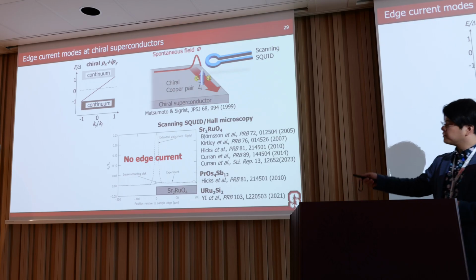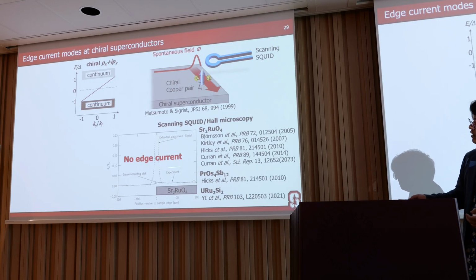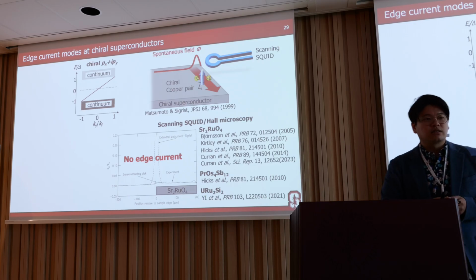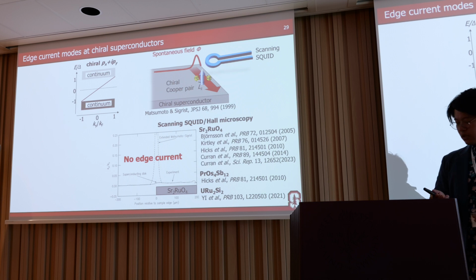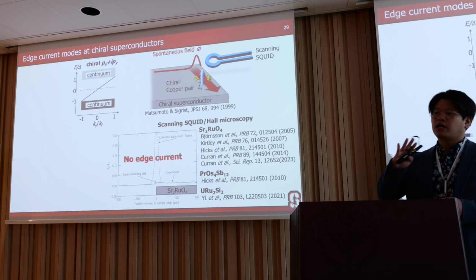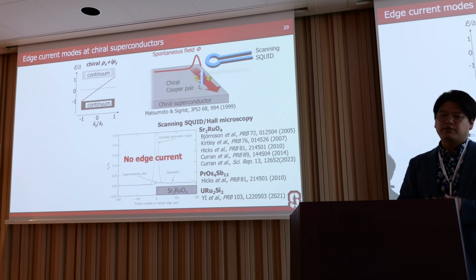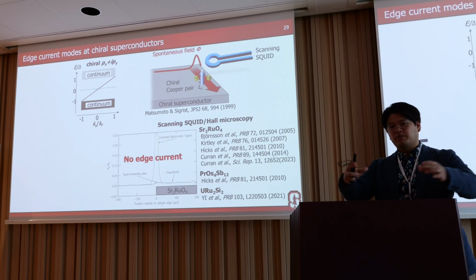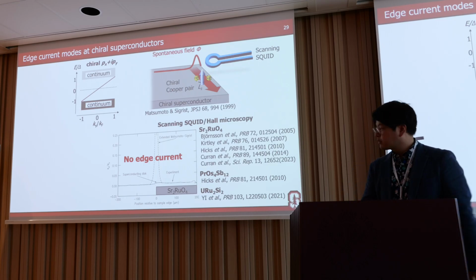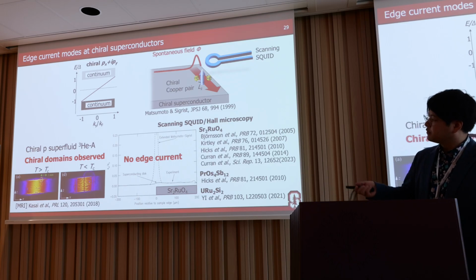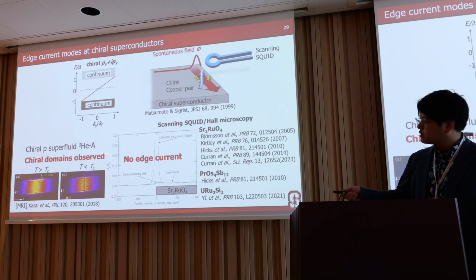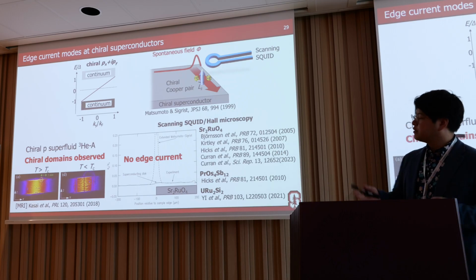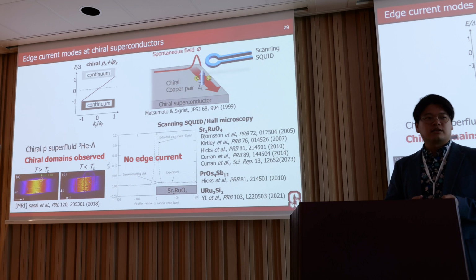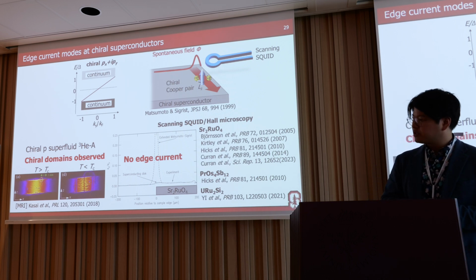Then our group and other groups measured strontium ruthenate and other samples, but we have never seen the chiral current, even though our noise level is much smaller. So every time we explain what the upper limit of the spontaneous magnetization is, or we estimate the upper limit of the domain size, smaller than our spatial resolution. In chiral superfluid, chiral domains are observed in real space at the millimeter scale. It's very large. So if we have better spatial resolution or other crystals, then we hope we can still measure chiral domains or chiral current in a chiral superconductor.